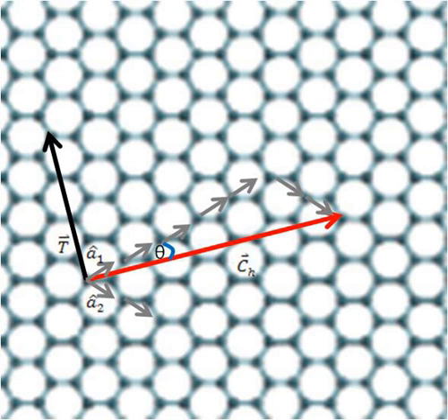This is due to the fact that the periodic boundary conditions for the one-dimensional carbon nanotubes permit only a few wave vectors to exist around the circumference of carbon nanotubes. Metallic conduction occurs when one of these wave vectors passes through the K point of graphene's 2D hexagonal Brillouin zone, where the valence and conduction bands are degenerate.